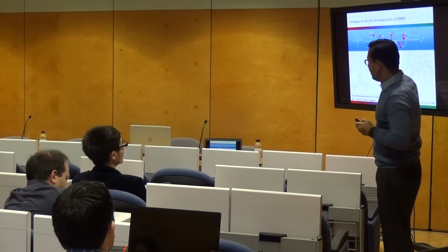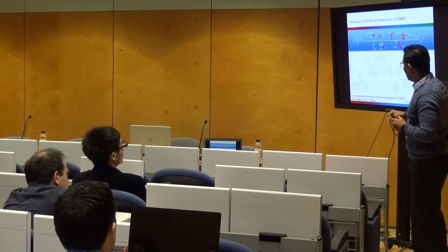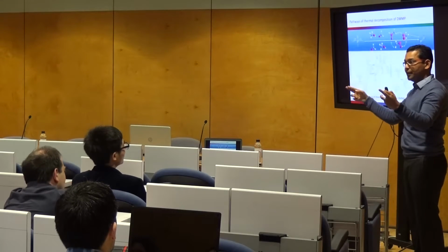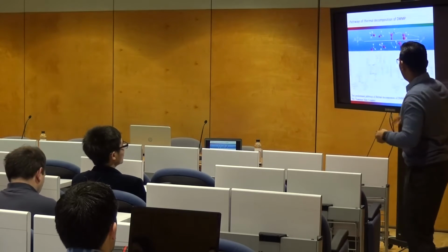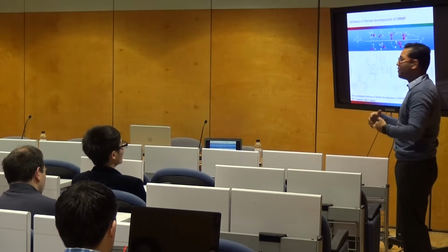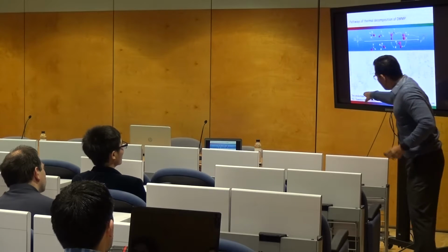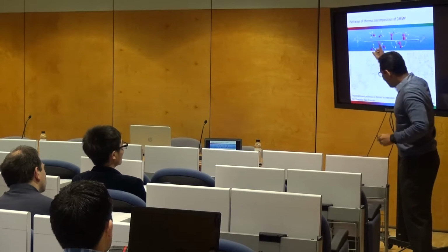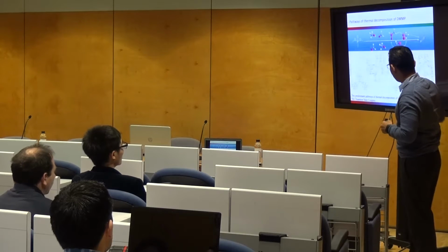So we know which species are being formed. We just have to draw the transition state, and to do the transition state, you need to do molecular modeling, I would say. We do all this modeling, we try to fit the experimental data to the model, and finally we come up with these pathways. Okay? So you can see DMMP, which has never been, I would say, proposed, we published already.